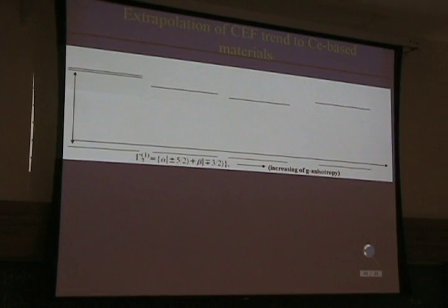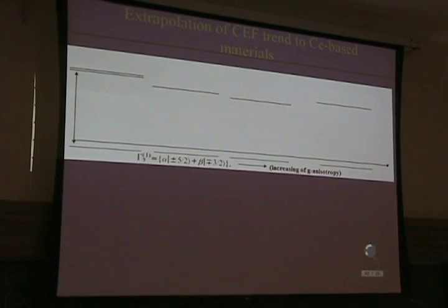So we know for a fact that these wave functions are changing, and that may increase g anisotropy. You can go from a cubic Gamma 7 with a totally isotropic spin to a different crystal field Gamma 7 state, which is very anisotropic. We put the field in different directions, and the Zeeman splitting is very anisotropic.